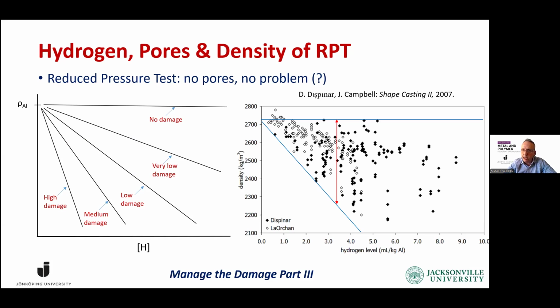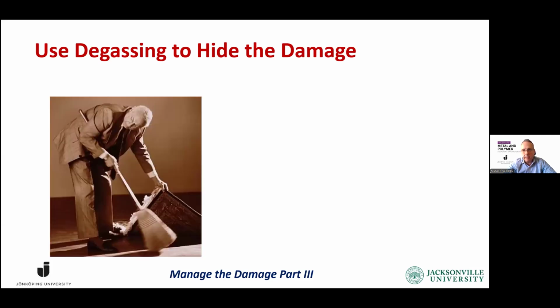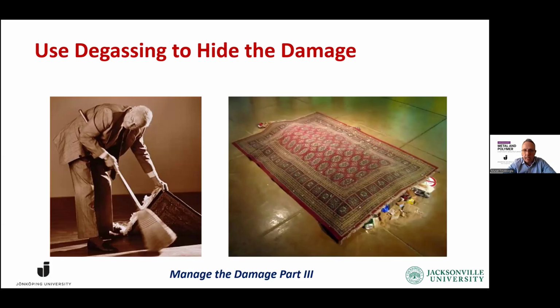But by reducing the hydrogen content, we're basically shutting off that information. So what that does is we're basically using degassing to hide the damage. We're sweeping the dirt under the rug. And if it's under the rug, it doesn't exist. If I don't see it, it's not there. Unfortunately, life is not that simple, because they come back and present themselves when the casting is under performance, under stress.